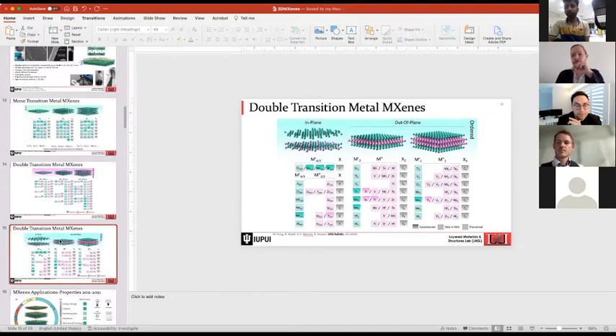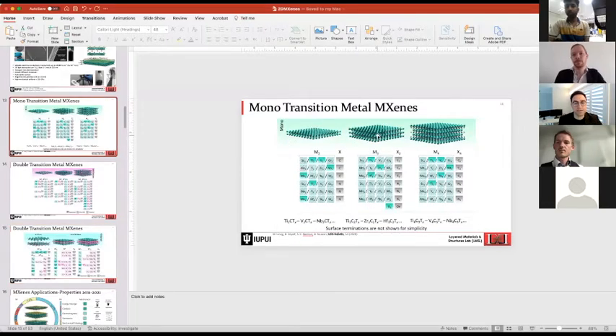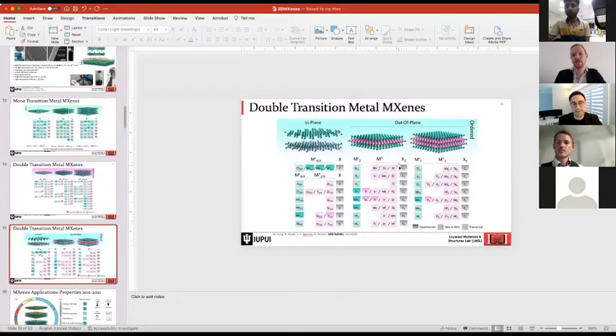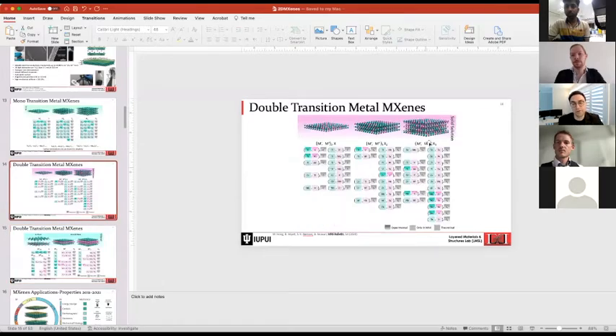So there are a few ways. One is to modify the core MXene structure, meaning that it has been shown that when we go, for example, from a Ti3C2, which is highly electrically conductive, to other MXenes, for example, the ordered structure where we have chromium or molybdenum on the surface and titanium in the middle, or even solid solution where we have carbon nitride, the electrical conductivity significantly drops.